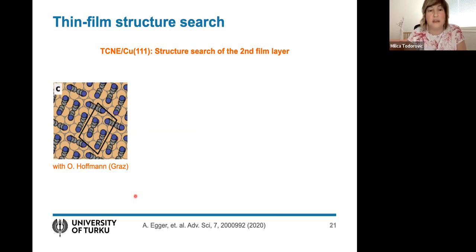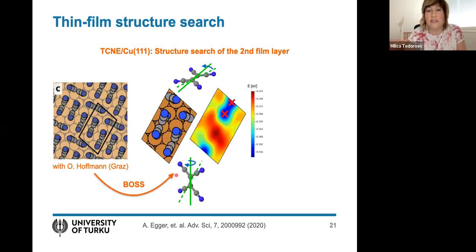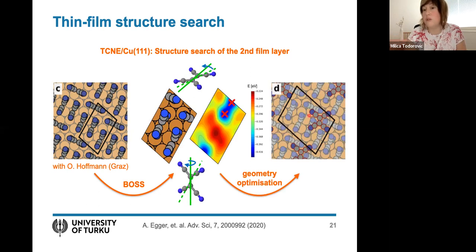So what we did is we took this unit cell of the monolayer, and we did a structure search of TCNE on top of this monolayer only in terms of position above the surface and some orientation in terms of angles. And we found the lowest energy structures. And this is how we knew that the next molecule would adsorb flat on top of these perpendicular molecules in the region where the molecules don't quite connect, and then this next molecule sees a little bit of the copper surface. So this was obtained by geometry optimization. And now that we know how the second layer was built, we could understand how the charge transfer penetrates from the inorganic substrate into the organic layer in some kind of functional device.